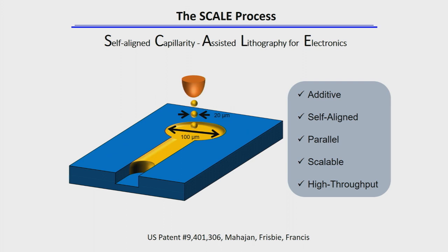So my colleague in the Department of Chemical Engineering and Materials Science, Lorraine Francis, and I have been thinking about this a lot. We had a really excellent student, and together we came up with an idea for this problem that's now patented. We call this solution self-aligned capillarity-assisted lithography for electronics. So just as a mouthful, let's call it the SCALE process. And the idea is that we're going to take a plastic substrate, and we're going to imprint it or emboss it with reservoirs, capillary channels, and device cavities. We're going to put complex topography into that, and that's shown here, reservoirs and a capillary channel, and what's not shown is a device cavity. Then we're going to use banks of inkjet heads to deliver drops of ink to the reservoirs, and then we're going to let capillary forces pull that ink out spontaneously and deliver it to the device cavity.